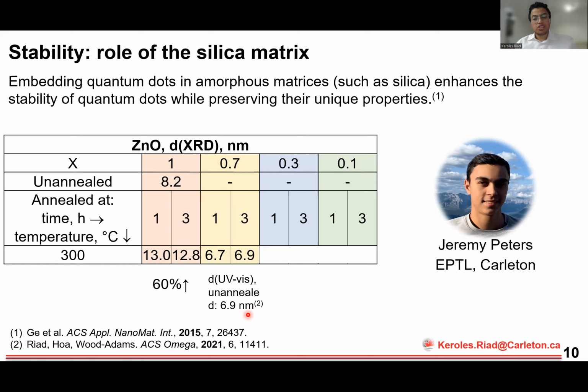There's an important distinction to make of what size is actually measured with XRD and UV-Vis. With XRD, you measure the average crystal size. With UV-Vis, because you measure onset absorption, you actually measure the largest crystal size. So there's a bit of a shift in the size distribution because of annealing, but it's not as significant as with pure zinc oxide. Now, with x equal 0.3 and 0.1, there's no growth sufficient to detect the crystal size with XRD. So there's still a lot more work to do here to have a complete picture. But so far, the data we have does not contradict the literature that the silica actually stabilizes the quantum dots.